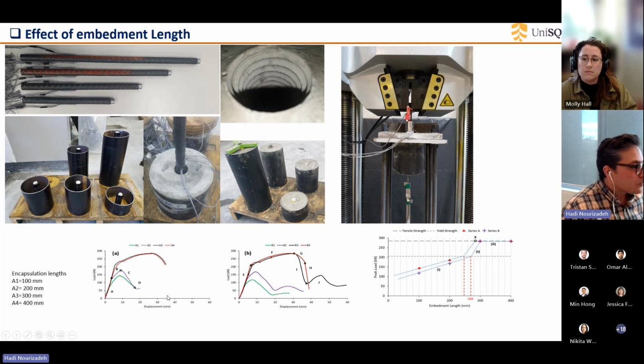As you see in the diagram here, by increasing the embedment length, we have higher bearing capacity or axial capacity. But comparing these two, we see that the type of bonding agent also affects this behavior. For example, for type A encapsulation agent, when the encapsulation length is over 300 mm, we have bolt rupture. It means that for this specific bolt, this specific surrounding rock, and this specific grout, which is A, the critical embedment length is around 300 millimeters.